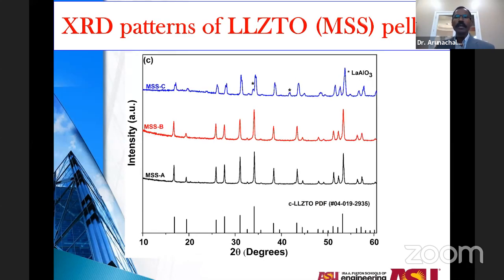But in the molten salt case, when the pellet was sintered along with the alumina as a sintering aid, we also obtained some impurities like lanthanum aluminum oxide. That could probably lead to lower ionic conductivity. Whereas with the platinum, there was no alumina.